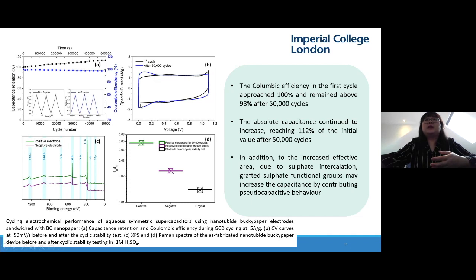But then there's a huge redox peak at nearly 0 volts, which we further characterized with XPS and Raman spectroscopy techniques. The XPS detects the surface functional group in both positive and negative electrodes, and the ID to IG ratio of the electrode is increasing compared with the original electrode before starting the cycling stability test, which confirms that there is grafting of the functional group on the surface of our nanotube bucky paper on both sides. In this case, we can refer back to the reason why the capacitance is increasing, because the surface functional group contributes to the pseudo-capacitive behavior in the system.